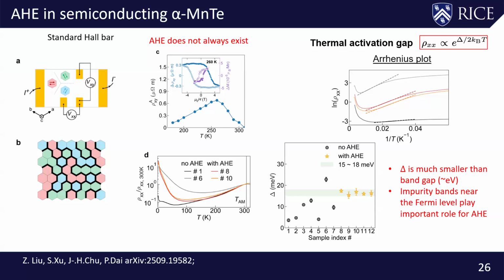It turns out only about 5 samples show anomalous Hall effect, and these are only the samples that are semiconducting with a charge gap of roughly 15 or 18 millielectron volt. And 15 to 18 millielectron volt is roughly around room temperature, or 200-some Kelvin in terms of its energy scale. That really suggests to us that this anomalous Hall effect is not only associated with the material itself, but also associated with impurity doping onto the system, so that your charge gap is roughly in this regime, and that's the only case in which you actually see anomalous Hall effect in this system.